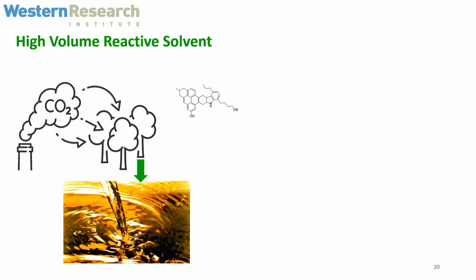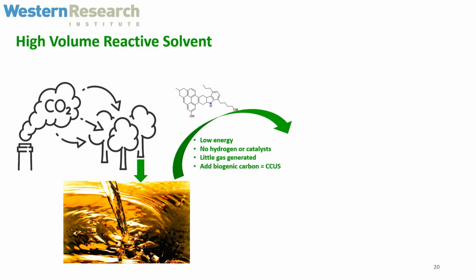Well, one thing that could make sense is that there's quite a bit of plant-based, animal-based oils available. And there's already a huge industry to take those, collect those, extract those. And what we found is that we can actually use those, particularly the fatty acids, and we can put them in a process that's relatively low energy. We don't need hydrogen. We don't need catalysts. We're not generating any extra gas in this process.